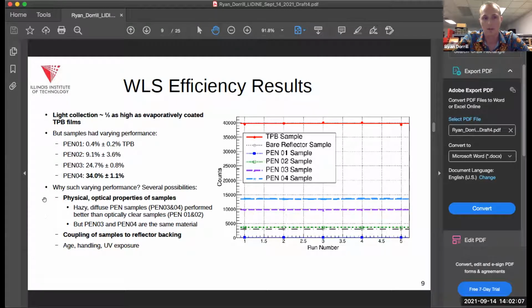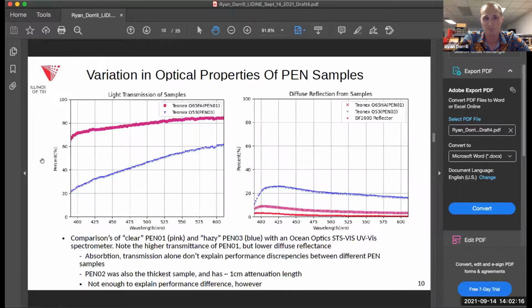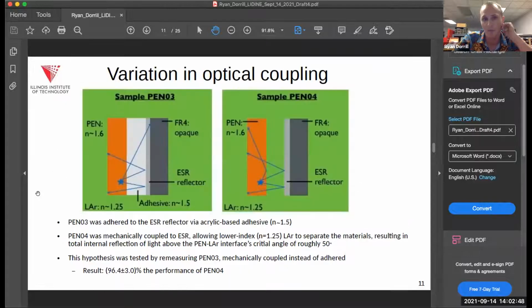We wondered if this had something to do with the UV wavelength shifting properties. There's also potentially the handling and the coupling to our reflector. So we tested some of these optical properties with a UV-vis spectrometer. The results, at least to me, were as expected: the very clear PEN samples transmitted light better, and the hazy ones had lower light transmission. And then, kind of flipping, diffuse reflection off the samples was higher for the hazy samples and much lower for the very clear samples. So that kind of made sense, but it didn't explain all the discrepancies we saw.